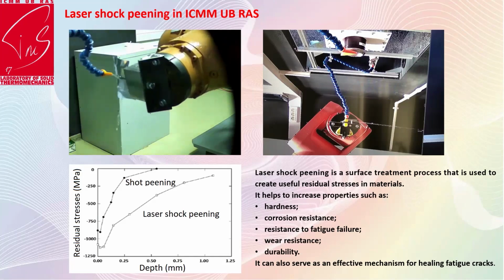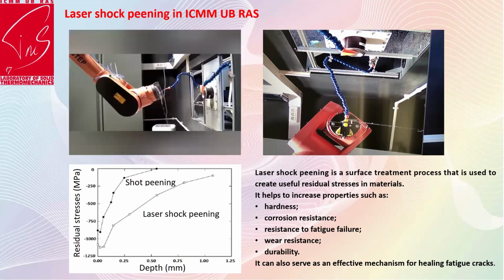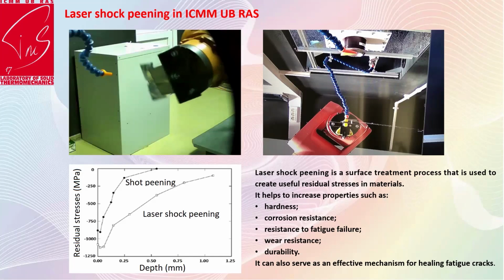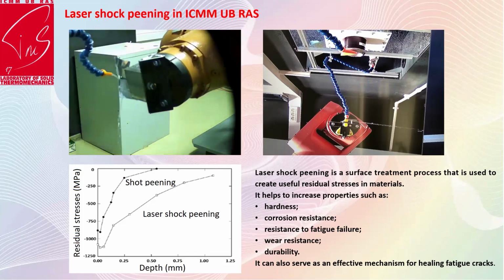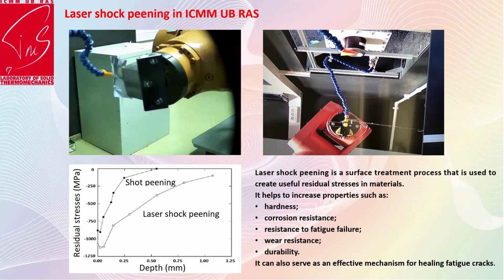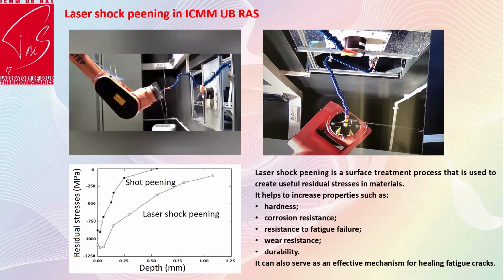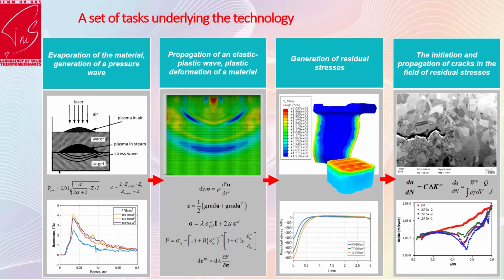If you compare shot peening, the standard technique used in our industry, and laser shock peening, you can see easily it's bigger and deeper. But there is at least one problem. If you have such a technique, all in all, you have a balance. If you create compressive residual stress in one place, you create tensile residual stress in another place. It could be inside of a sample, it could be on the sample surface. And it's really a big problem. I have only a few minutes, so I will just show you what we are doing.